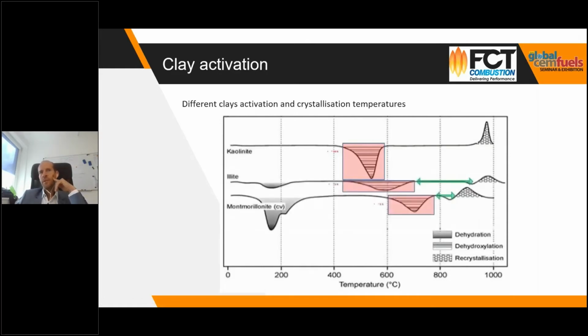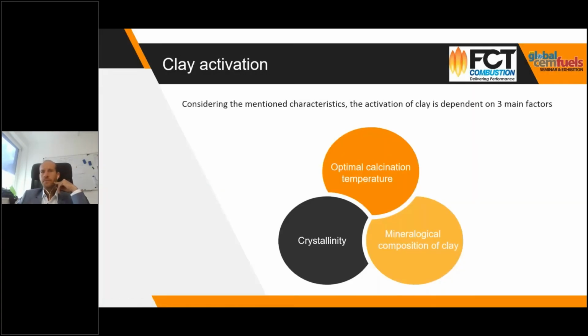From the other two types that we showed before, we have illite. You can see that the temperature range for activation is a bit longer and closer to the recrystallization zone. And montmorillonite is the most difficult of these three to activate, because the end of the activation and the beginning of the recrystallization are very close together. So you need here a very good and tight temperature control in your process.